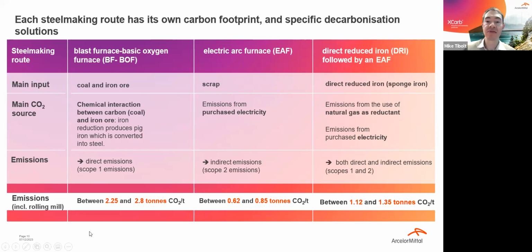In the middle column, we see the electric arc furnace, the secondary route, where we produce steel out of scrap. So the starting point is no more iron ore or coal, but scrap, that we melt in an electric arc furnace using, of course, electricity. That's why the main CO2 source is coming from the purchased electricity. And here the emissions, also including the rolling of the products, lie between 0.62 and 0.85 tons of CO2 per ton of steel produced. So it's already less than from the blast furnace.